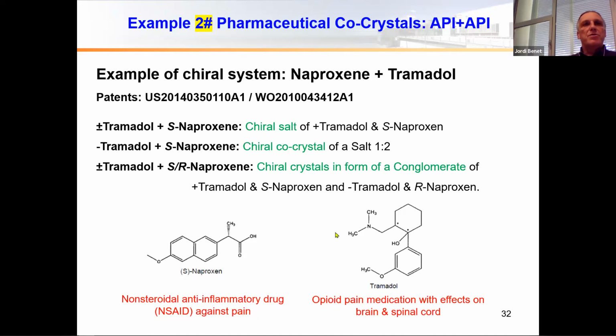And so when you join these 2 molecules and try to crystallize them, these are chiral molecules, if you take the racemate of tramadol and S-naproxen, you get a chiral salt of this compound, which is plus tramadol and S-naproxen. If you use minus tramadol and S-naproxen, you get a chiral co-crystal with a ratio of 1 to 2, a chiral co-crystal of a salt. And finally, if you mix everything together and crystallize, you get a conglomerate with salts of plus tramadol, S-naproxen, and minus tramadol, R-naproxen. So you see, it's a quite curious system doing quite strange things. So we decided to study a bit more about these solids.